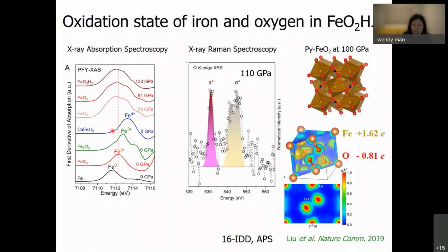So we also conducted an X-ray Raman spectroscopy study to look at the oxygen edge. This is a very challenging measurement since we cannot access the oxygen K edge directly. At 540 electron volts, this would be a soft X-ray measurement and we require vacuum. So we had to do this X-ray Raman measurement, which is an inelastic measurement where we shift the incident and the scattered X-rays into the hard X-ray regime. The difference between the incident and the inelastically scattered X-ray energy is the oxygen edge.